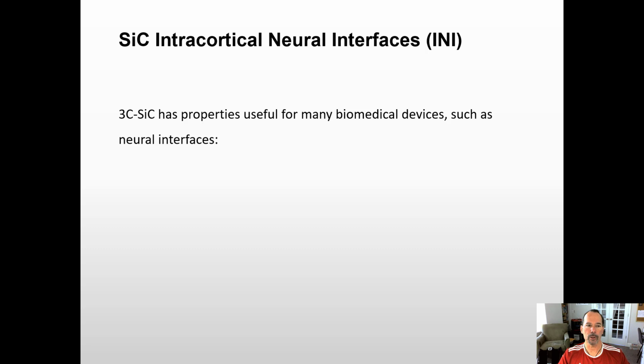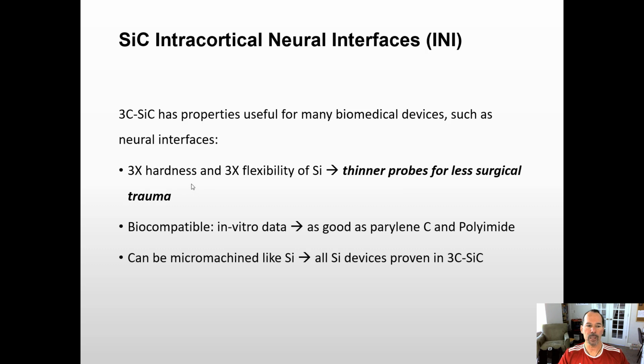So let's talk a little bit about why we think this is useful for biomedical devices. We have 3 times the hardness and 3 times the flexibility of silicon as a basic material, so we can make thinner probes that would produce less surgical trauma. So being able to thin things down and make them smaller scale has been shown to greatly enhance the compatibility of the probe with the brain. Our in vitro data looks great. In fact, our material is as good as Parylene C and polyimide, and we also compared with gold for our conducting heavily doped silicon carbide, and it is as good as standard gold. So we're basically showing in vitro data that is as good as the best materials that are out there.